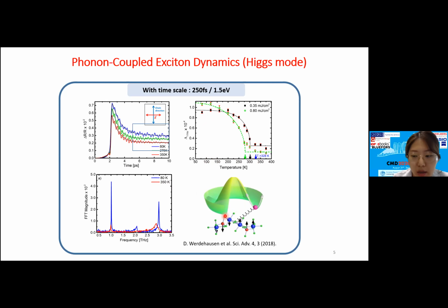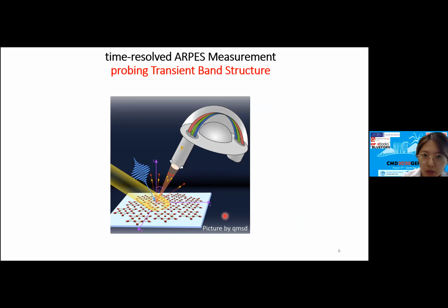exciton condensate. So the question is, can we see this exciton-condensation-coupled phonon mode also in the measurement of band gap dynamics directly? We can measure time-resolved ARPES to probe the transient band structure. There are 2 papers about it already.